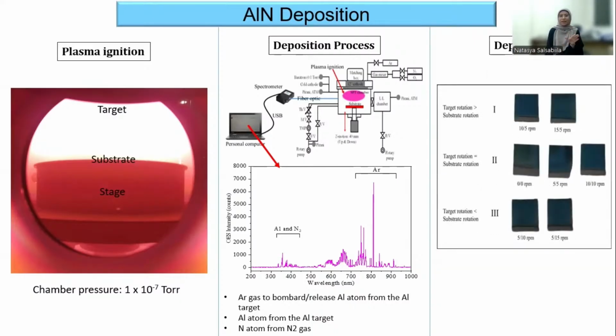To better analyze the effect of rotation, we group the settings into 3 regions. Region 1, where target rotates faster than the substrate. Region 2, where target and substrate rotate at the same speed. And the last one is region 3, where target rotates slower than the substrate. From this figure, we can see that the film from the 10 per 10 RPM setting shows a more uniform color, indicating better thickness uniformity.